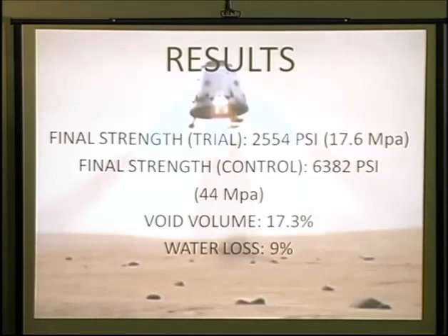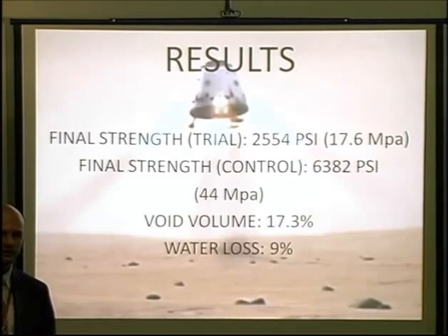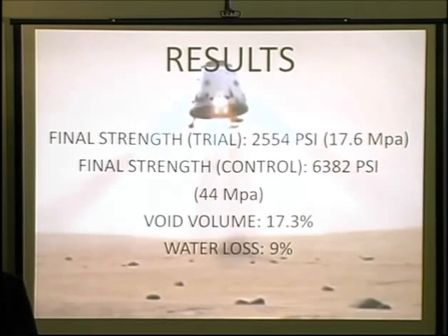The void volume in the trials in the chamber, I calculated just by the weight of the samples, was 17.3%. I also weighed the samples before I put them in the chamber and then afterwards to measure the water loss due to evaporation, and it was only 9% of the total water in the cement, in the concrete. Now, to account for the strength loss due to the void volume.